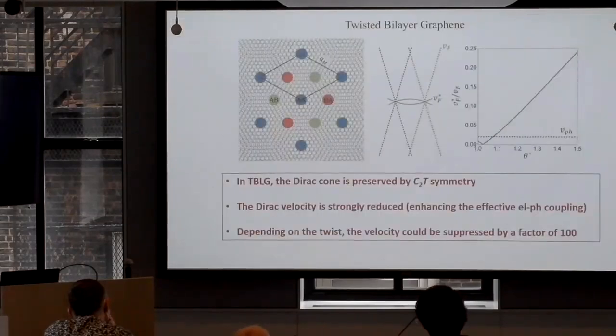So now we need to take that graphene and convert it into twisted bilayer graphene. This is the picture. Basically, we use the same band structure everybody uses, the MacDonald band structure. And this is a calculation of the graphene Fermi velocity as a function of the twist angle. This is the famous magic angle, where in this zeroth order theory, the velocity goes to 0. Now, this is the Fermi velocity of graphene. This is the phonon velocity of graphene.